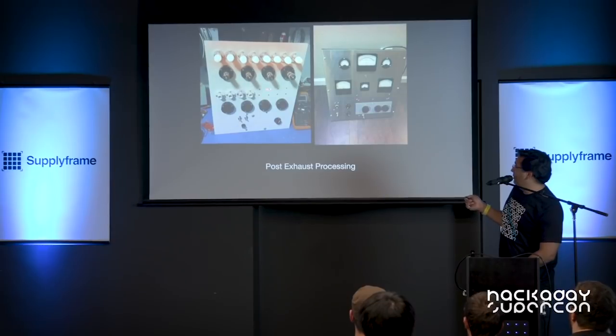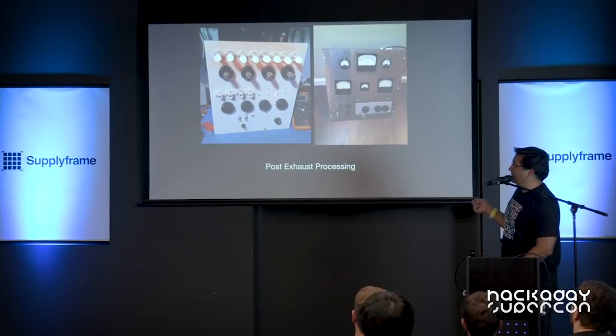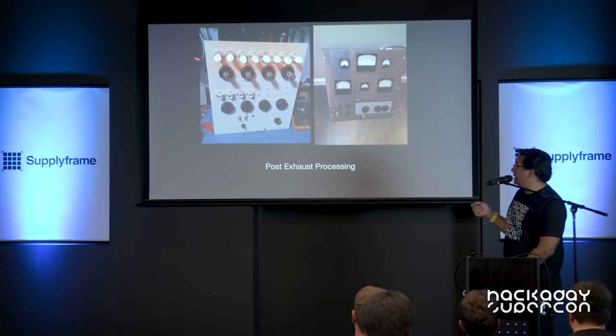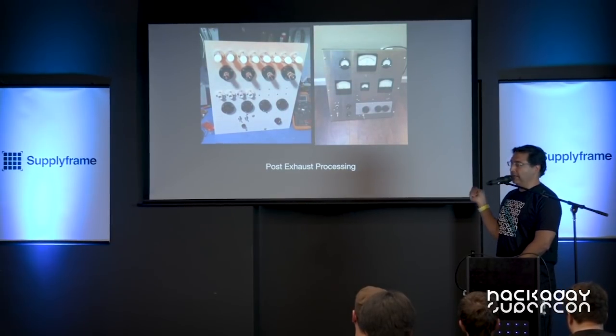After it's cooled, you process the tube by aging it. Each design has a particular sequence of voltages and currents applied, which activate, if it's an oxide-coated cathode, which would sublimate the oxide metal of your particular cathode to the surface, providing your emissive surface. And they will come up in emission as time goes on. And then dynamic testing for mutual transconductance, leakage, and so on.